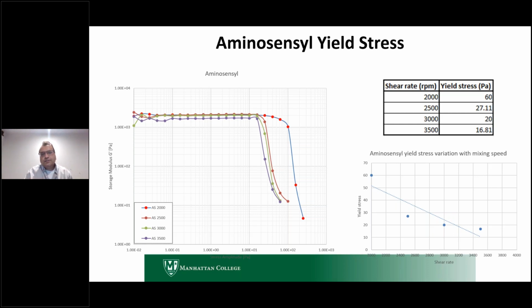So what we did was in each of these 6 reactors, we applied different rates of shear when we were making these formulations, going from a shear rate of 2000 to 3500. And we wanted to explore what that shear rate does in terms of affecting this yield stress or this interconnectivity. And we see that it has a very nice relationship. With the higher shear rates, you end up with lower yield stresses, so systems which break apart the structure more easily, right?